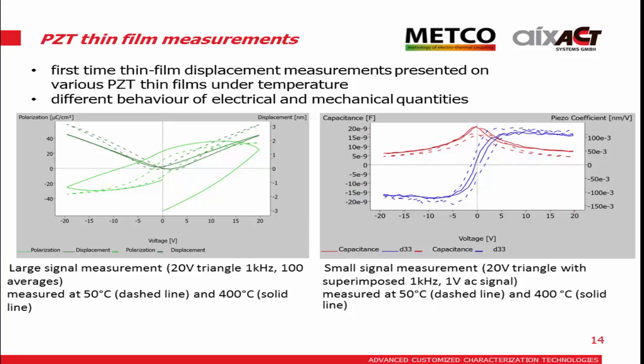At high temperatures, our electrical values are mainly influenced by leakage currents, and that means we can't really trace the polarization. Of course this is also frequency dependent, but we can still see that the deflection, or the piezoelectric activity, is still quite high - about 3/4 of the room temperature value, and this is measured at 400 degrees C.